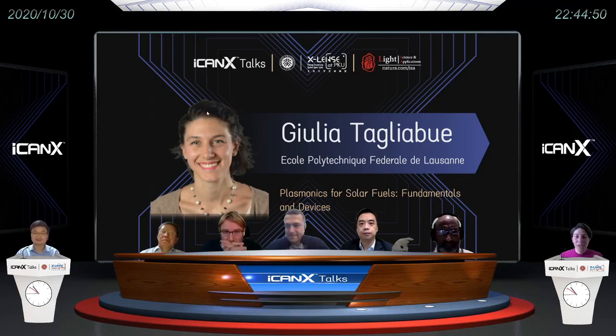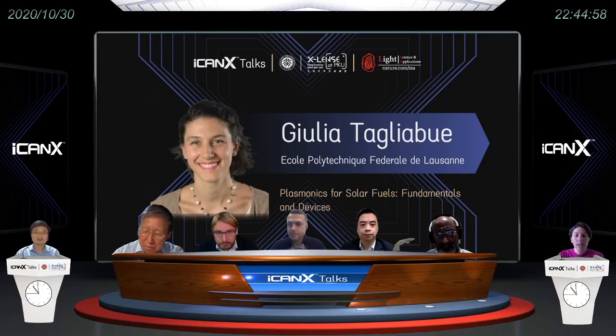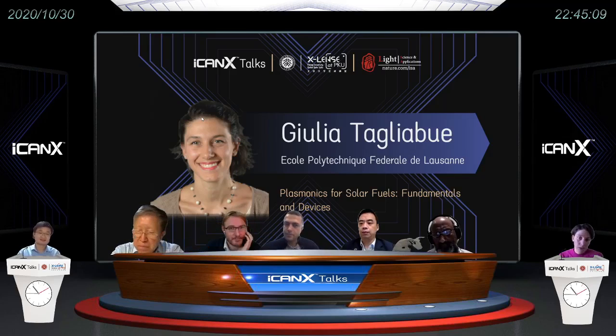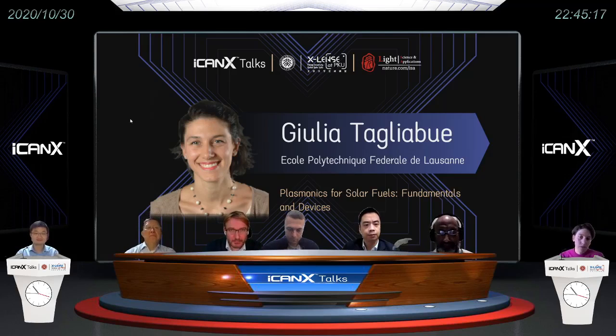Yes, this is a very good question. One of the advantages for the CO2 reduction aspect is that it's a reduction process. So typically, we do still need to apply a little bit of a negative bias to the electrode to be able to drive the reaction. And this negative bias has already been shown to be sufficient to re-reduce any kind of oxide that might have formed, especially on copper. This is a major issue on copper. And we know from other experiments from other groups and our own experiments that the oxide layer can be re-reduced back to native copper.